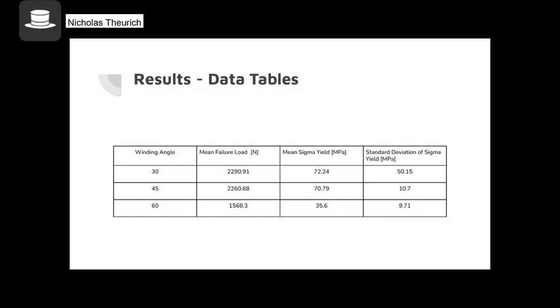As can be seen in our results table, our 30-degree winding angle had the highest mean failure load at 2290 newtons, as well as our highest mean sigma yield at 72.24 megapascals. However, this dataset does have a very high standard deviation, which was due to some manufacturing defects that will be discussed in a later slide.